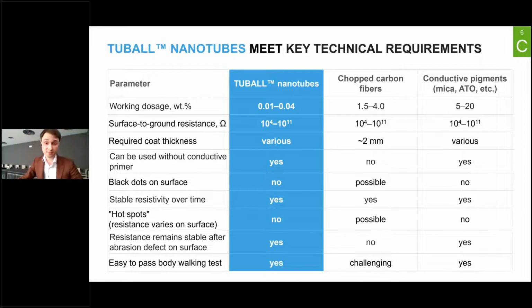One of them is, of course, chopped carbon fibers. It is a very well-known agent, but it still has some drawbacks. First one is the limitation of base coat thickness. Generally, due to technology and average length of chopped carbon fibers, the base coat thickness is around 2 millimeters, because you need to orient chopped carbon fibers, and this is the main limitation. Also, the usage of chopped carbon fibers can be quite sensitive, and in many cases can lead to hot spots, which is flooring area with insufficient level of resistivity and some black dot spots on the surface, which is not very good for aesthetic properties. And if you damage some anti-static flooring with chopped carbon fiber, there is a high risk that you can lose the required property as well.